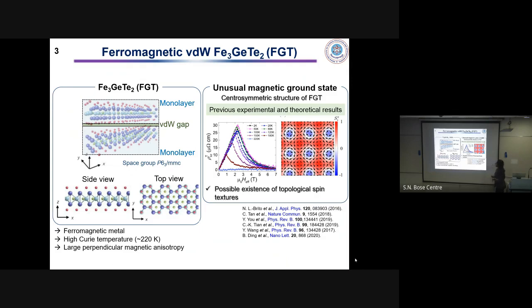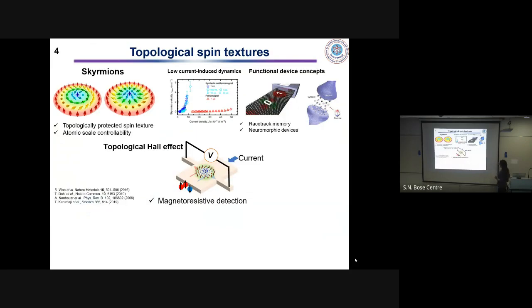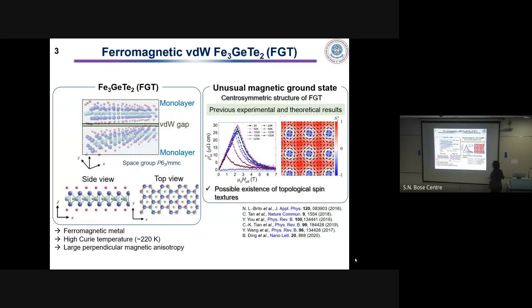Moving on to the crystal structure of Fe3GeTe2, it consists of Fe3Ge sublayers which are sandwiched between tellurium layers, and there exists a van der Waals gap in between the adjacent tellurium layers. Another feature that makes Fe3GeTe2 even more interesting is that it has a simple centrosymmetric crystal structure. However, recent theoretical results have shown that this system can possibly host topological spin textures in it.